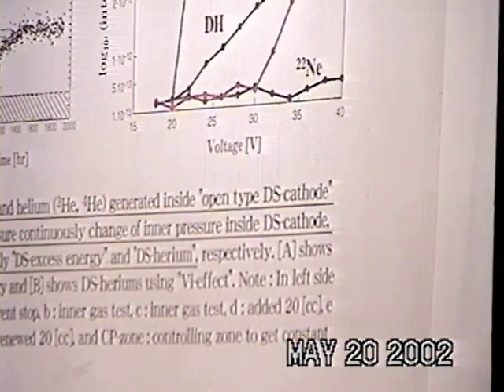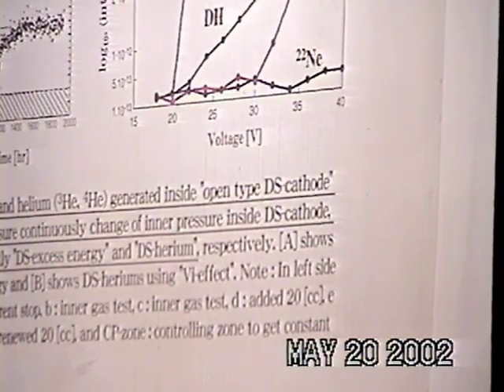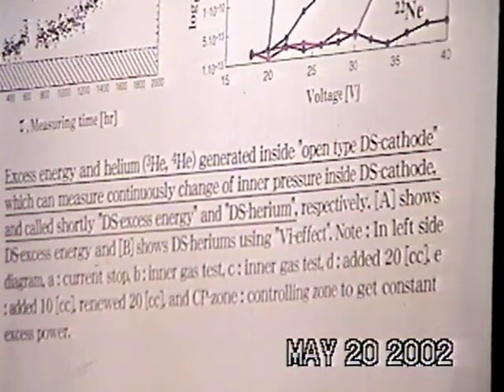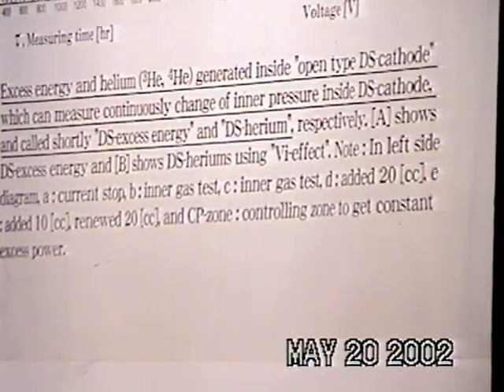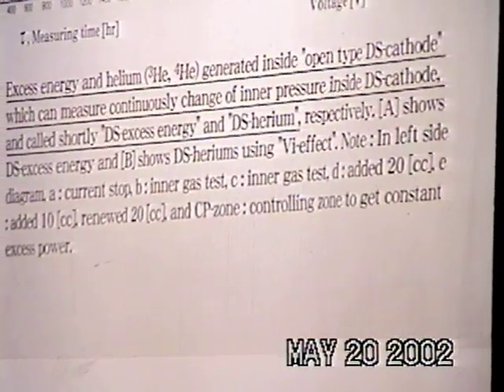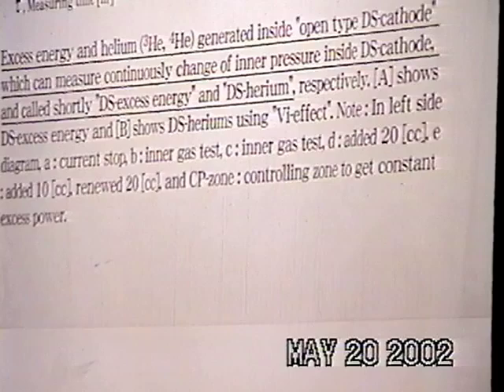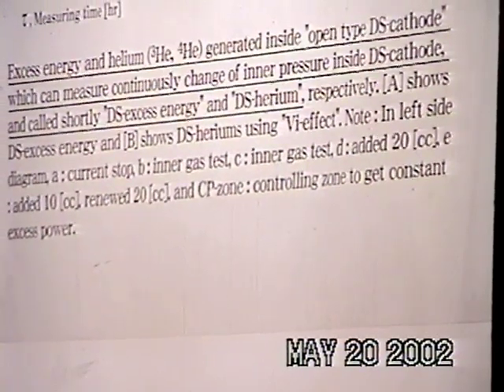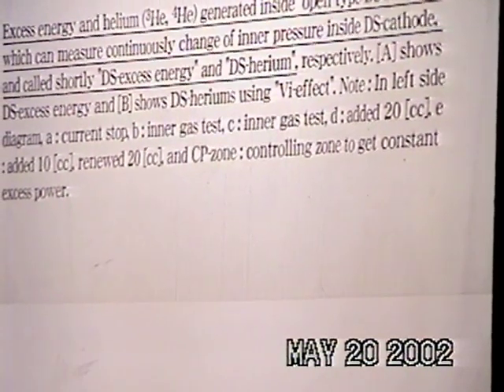To measure continuous change of inner pressure inside the DS cathode, we call them DS excess energy and DS helium, respectively. A shows the left side, DS excess energy, and B shows the right side, DS helium, using the VI effect. Note, in the left side diagram, at A the current stops, and at B inner gas is added to 20 cc, and 10 cc renewed 20 cc, and the CP zone is controlling zone to get constant excess power.